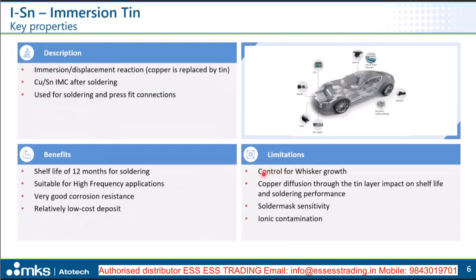So there are some limitations which need to be considered for the immersion tin process. There is a certain risk for whisker growth, which is kind of process inherent. Whiskers typically grow caused by the formation of the intermetallics during the aging of the immersion tin layer. This formation of the intermetallics then causes stress, and this may lead to whisker growth. So there need to be approaches to prevent whisker formation for immersion tin layers. For sure, we don't have any barrier layer here, so there is a certain copper diffusion through the tin layer, which in the end limits to a certain extent also the shelf life of the finish.